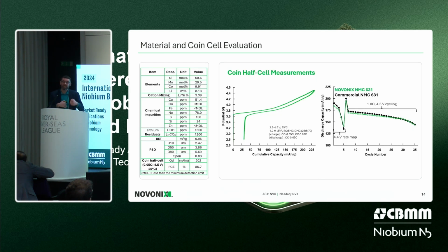So this powder itself has very standard, typical properties of a single crystal NMC631. Particle size is on the order of what one would expect for NMC631. The impurity profile is quite low. We'll put that in a coin half cell, and the voltage curve shows that it looks like NMC631. We even ran some head-to-head rate testing on our powder as compared to a commercial NMC631, and the results are pretty comparable, right? The rate mapping is competitive, and the longer-term 1C cycle testing at 4.5 volts is pretty competitive.